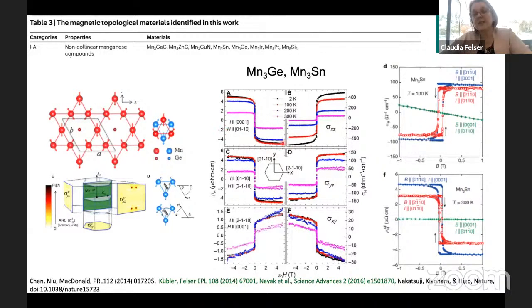But here in this measurement, you see the anomalous Hall effect, you see here in the Hall measurement as a function of the magnetic field, and you see here this nice jump in the anomalous Hall effect in the manganese germanium and here in the manganese-3 tin, and it's a giant jump. Experimentalists who are working on this kind of materials know that this is a really large effect, not a small effect. This cannot come from any impurity in the material because really it's a giant effect compared to the magnetization.